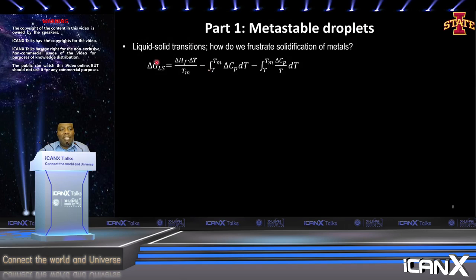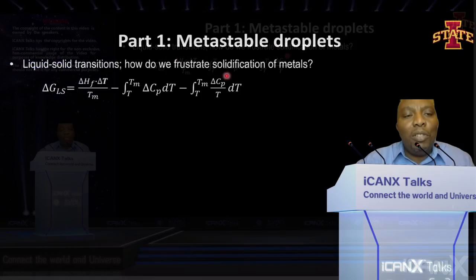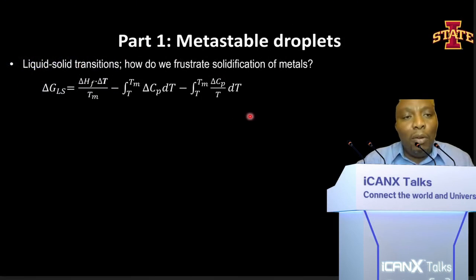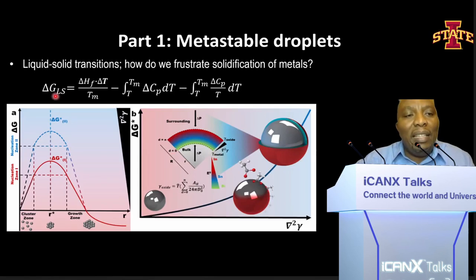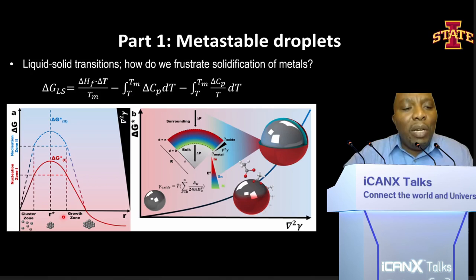So coming back to that idea of frustrating solidification, if you look at the classical nucleation theory, there is a gaping hole in the definition because you don't have any component here that is capturing the role of the interface that I just described. So if we want to understand in totality liquid solid phase transformation, we teach in our classes that once you eliminate heterogeneous nucleation, the only thing you need to worry about is homogeneous nucleation, which will be driven by nucleation and growth. And if I add an extra tension to this, can I have a situation where I inhibit the growth of this seed nucleus by raising the energy barrier significantly, and therefore inhibiting solidification to a significant amount?